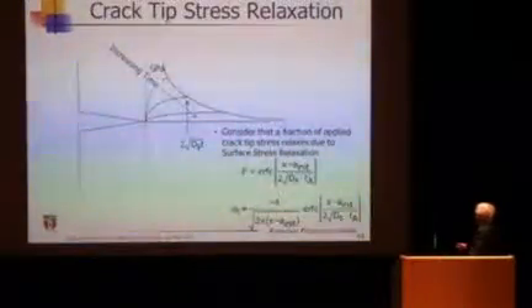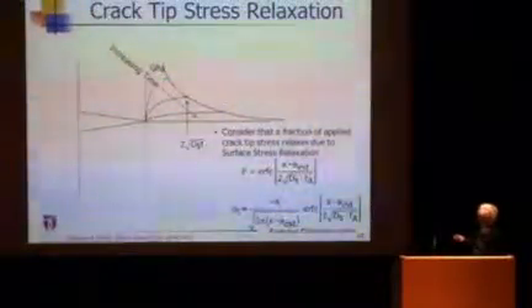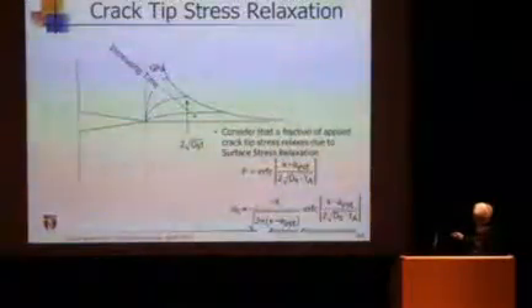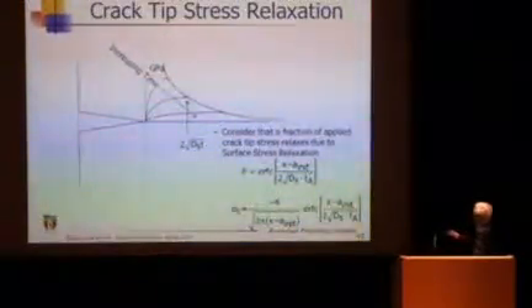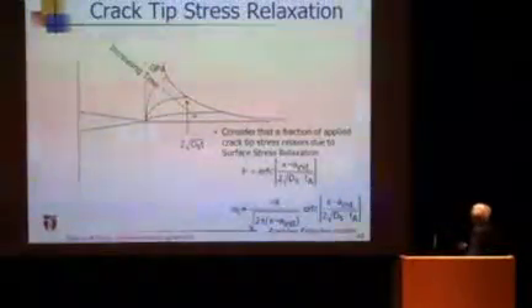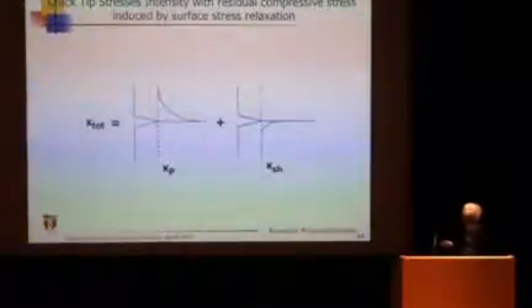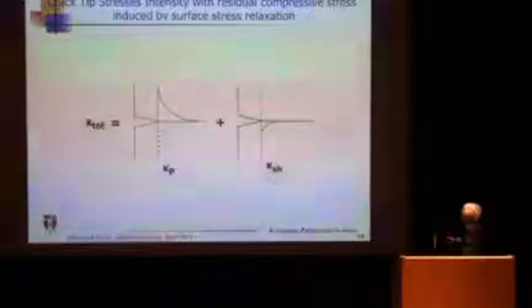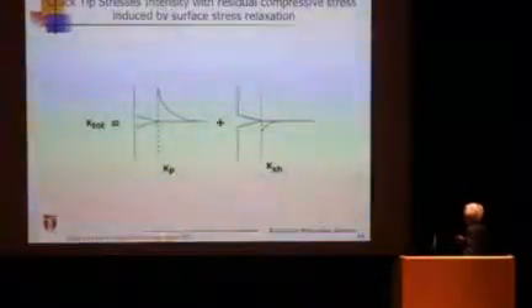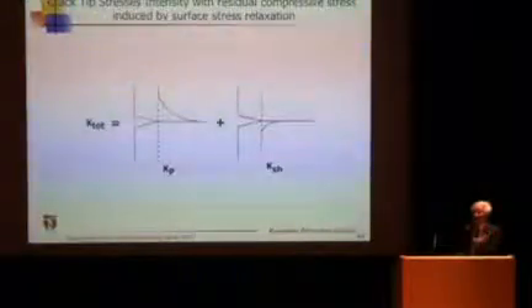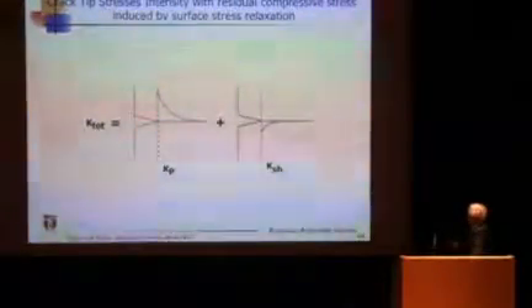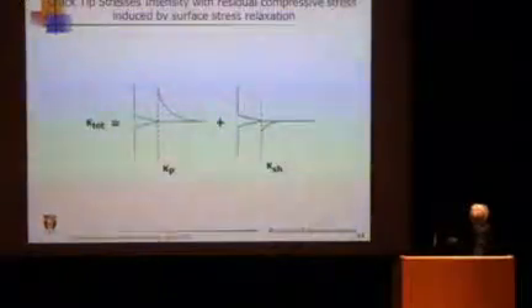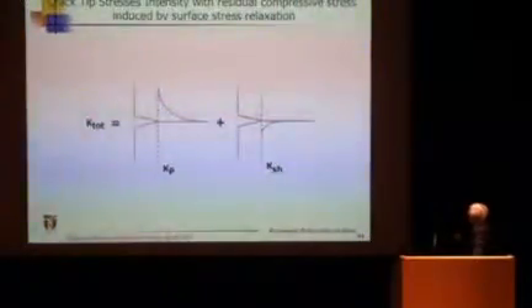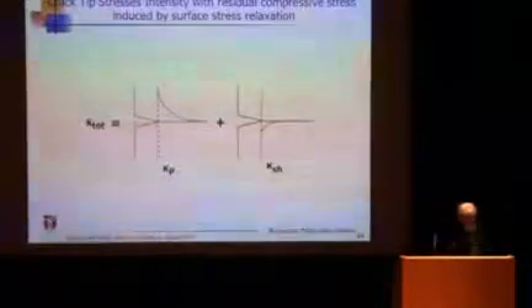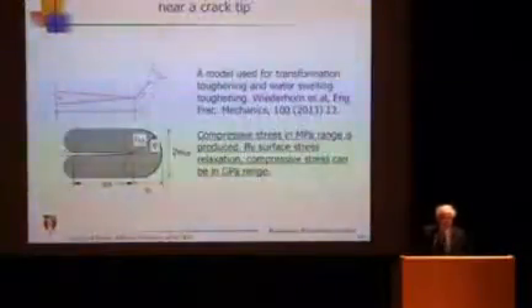And that would produce the force, that part would suddenly affect the crack propagation. And that part we can analyze in this manner: there is the original tensile stress, but relaxation reduces this, and we can superimpose that as a compressive stress. The relaxation produces effectively compressive stress. So we have to deal with this far stress field and the local stress due to compression. And that has an effect of shielding the crack growth.